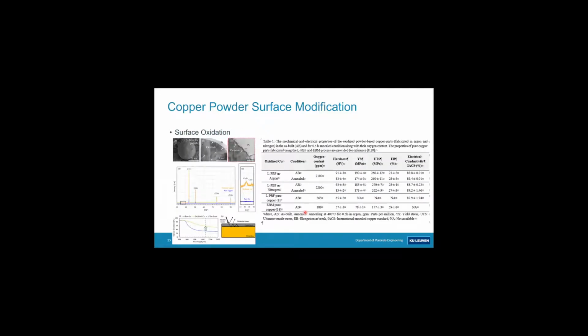The most simple way to improve the optical absorption of a powder, of a copper powder in this case, is simply to oxidize it. And so you noticed in XRD that there were copper oxides present at the powder particle surface. You also saw that in the powder state, the optical absorption was increased. And again, we could process this alloy at fairly mild laser powder bed fusion conditions, I would say. So again, about 500 watts of power with a scan speed of 700 millimeter per second. This is a summary of the properties we obtain.